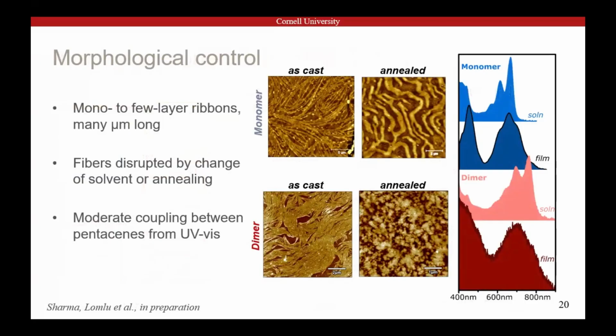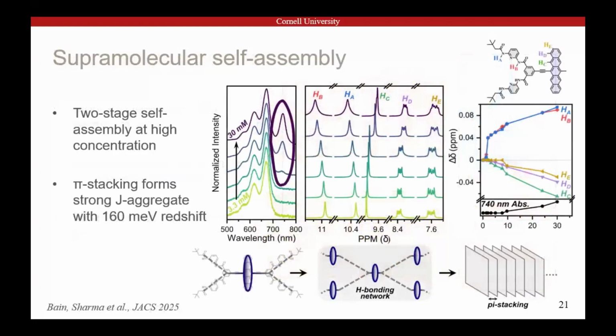So depending on processing conditions, we can get these beautiful micron-length nanoribbons or these more amorphous agglomerates. We can get very different kinds of coupling between them: H-type, amorphous, maybe J-type. At very high concentrations, we discovered a cooperative self-assembly mechanism where the pentacenes first form these hydrogen-bonded two-dimensional sheets, and then the sheets pi stack to form these beautiful, well-defined J aggregates, which have never been seen in pentacenes before. So we have this whole zoo of ways that the pentacenes can now couple together for us to explore.